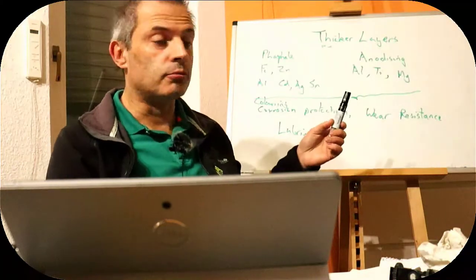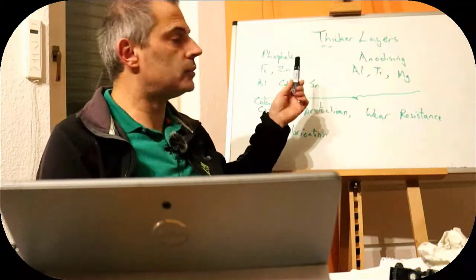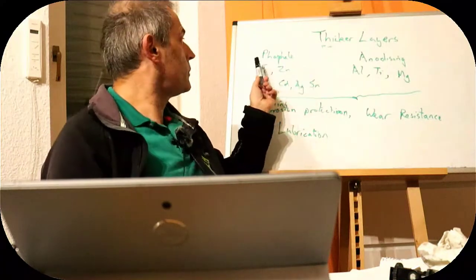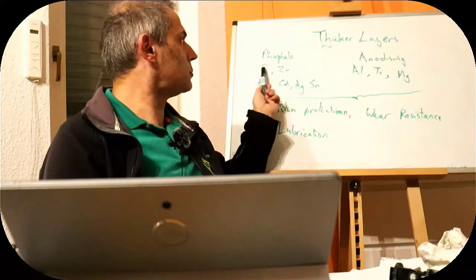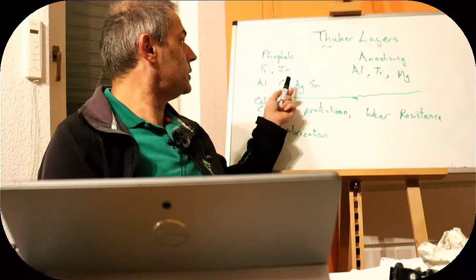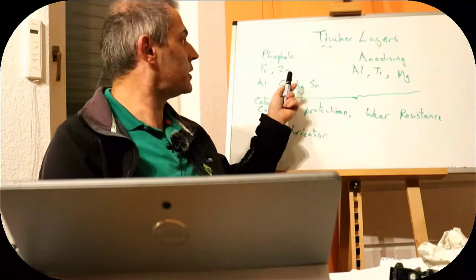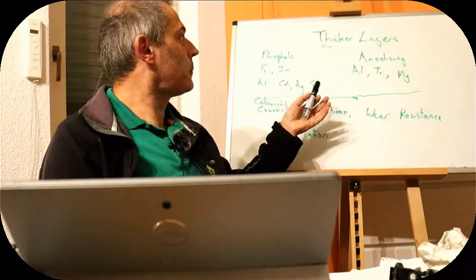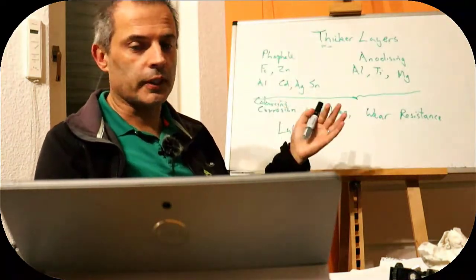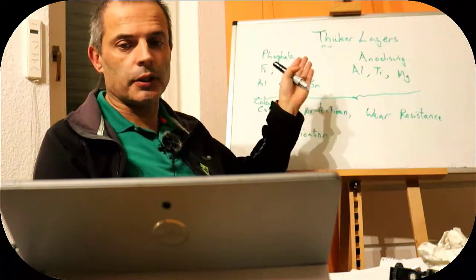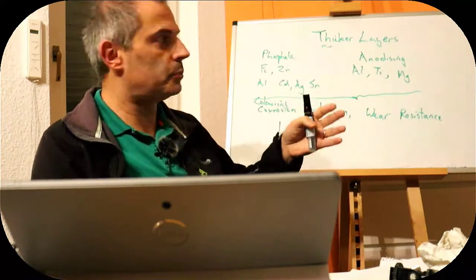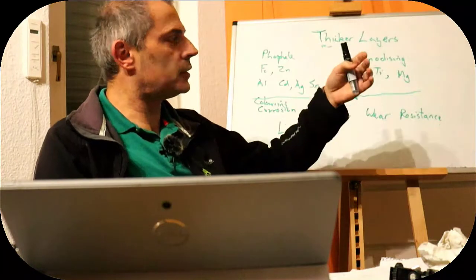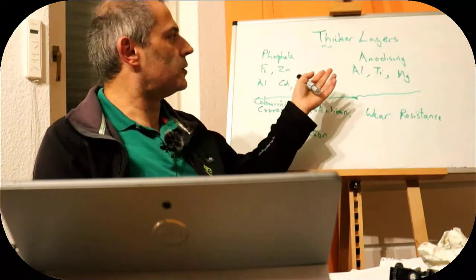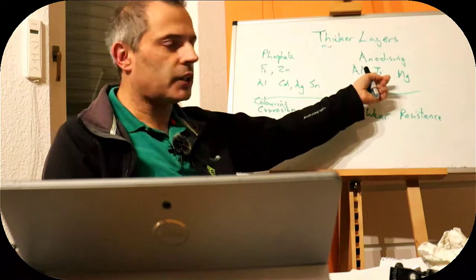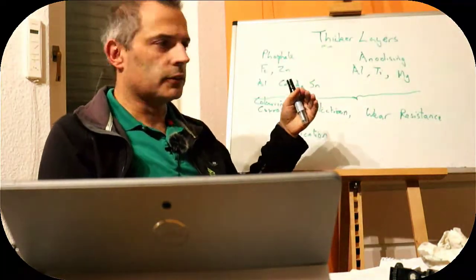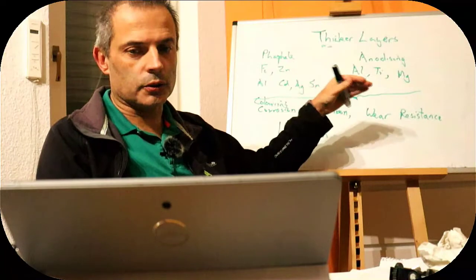So as we can see from this rough table, phosphating with some kind of phosphating mixture is good on ferrous metals, so iron and steel, zinc, aluminium, cadmium, in special cases, silver and tin. That generates an insoluble phosphate layer that's slightly soluble in acid but not very soluble in mid to high pHs. Then anodizing is not so good on most of these metals, but aluminium, titanium and magnesium in particular are very effective because we only get an oxide layer.